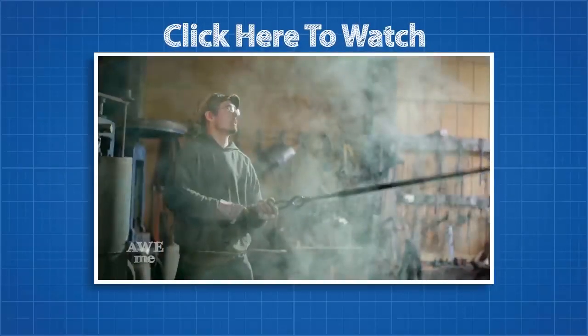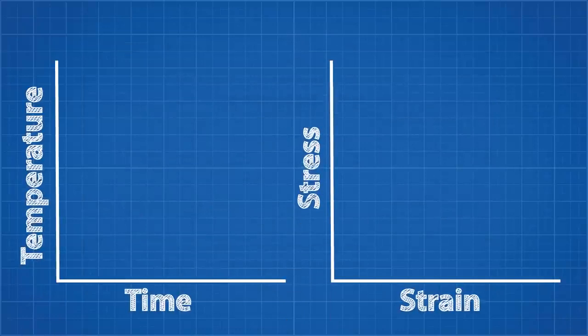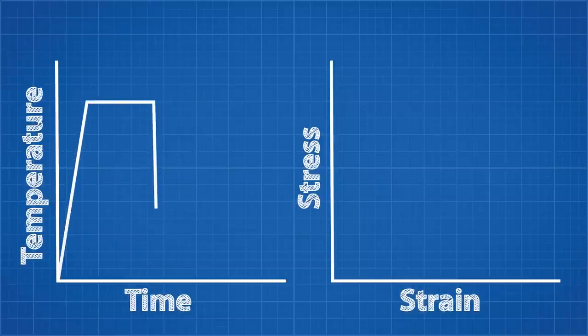As the story goes, one Friday afternoon, Alfred was testing a new alloy of aluminium he had developed containing about 4% copper. He followed the steps for quench hardening. He heated the metal up and allowed the heat to evenly distribute throughout the material. He then removed the metal from the heat and quenched it, rapidly cooling it. He then tested the material, but it showed no real sign of improvement.